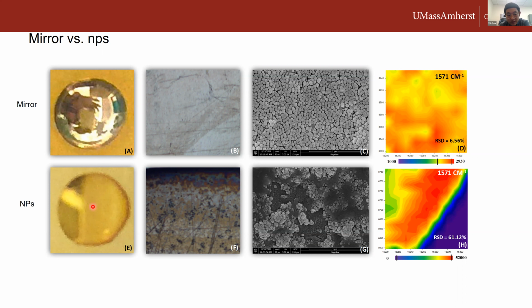This droplet will dry gradually, but one thing we cannot control is the evaporation, as you can see here in image E. On one side of this coffee ring, you will have very concentrated silver nanoparticles, like the edge is very thick and dark, whereas on the other side, that edge is very thin and not as dark. This creates a lot of variation. When testing under Raman, you will definitely detect a very high signal on one side instead of the other. This will pose a lot of disadvantages when you want to do quantification using these techniques. Also, if we look at image G, this is the image under SEM, and you can see all those nanoparticles are not uniformly located. You have different layers, and you have these clusters of silver, whereas the other part doesn't have those clusters.